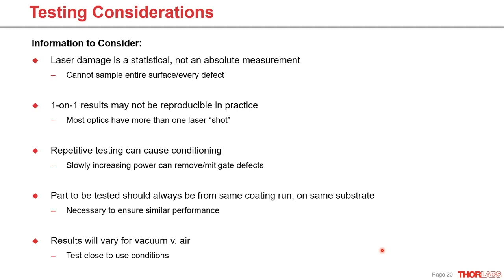You also want to be sure that when you're testing a part, this is a destructive test, so you're not testing what you're putting into your system. You're testing a sample of what you're going to be putting into your system. So you're going to want to test something from the same coating run on the same substrate, because, as we mentioned, laser damage threshold can vary from coating run to coating run, and it's certainly going to vary on different substrates. So you want to ensure that what you're testing is what you're planning on using to get the most accurate results possible.